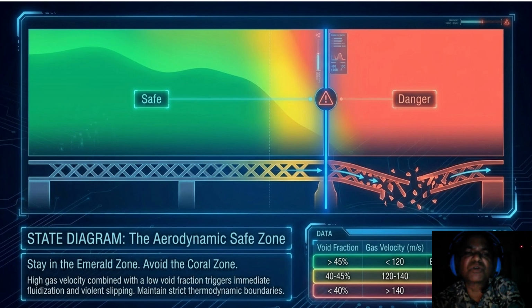This is not a suggestion, it's physics. High gas velocity combined with a low void fraction caused by those coke fines we talked about will lead to a slip every single time. Your job as an engineer is to maintain these strict thermodynamic boundaries. If you feel the furnace tighten up, you are already moving into yellow hanging residue. So this tightening of the furnace is often caused by scaffolding, which as we will see is violently coupled with our alkali input.